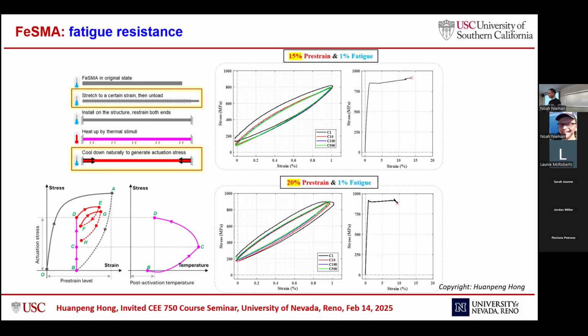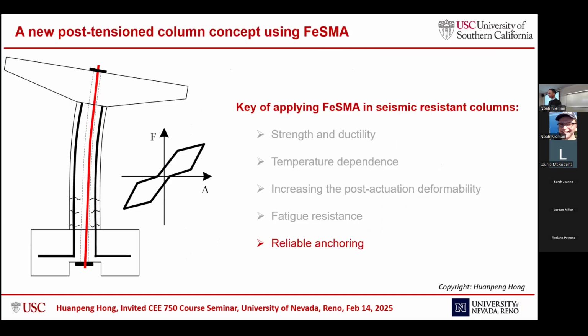Next, we also did fatigue loading on this material to simulate what will happen in earthquakes. We see here 20% pre-strain plus 1% fatigue, which is more than what we need in a bridge column. After around 500 cycles, this material is still stable, and there's still no fracture. After the low cycle fatigue loading, we stretch this material to failure monotonically. It still exhibits around 10% fracture strain, which is still comparable to conventional steel.